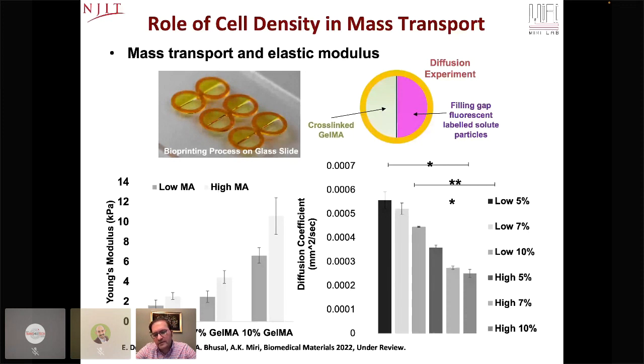You're all aware of the 3 different concentrations, 5, 7, 10. They change the stiffness because higher concentration means a stiffer microtissue. But something that we're very interested to see is what would be the diffusion property or the diffusion coefficient. You can see when you go from higher concentration to lower concentration, the diffusion actually goes high. So it's opposite to the modulus. So when modulus is directly linked to the mass concentration, diffusion coefficient is opposite.